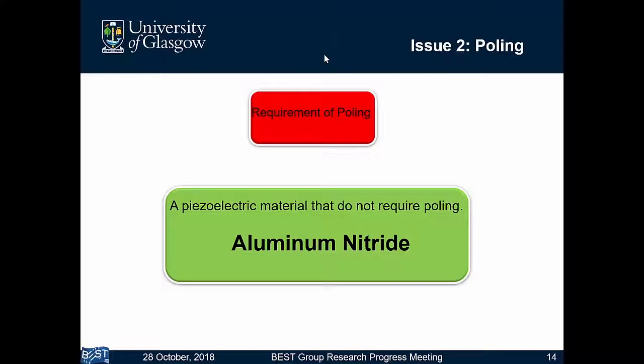The bad thing is that the piezoelectric coefficient is a bit lower compared to PVDF-TrFE, but still we see the advantage that it cannot damage my device. Anyway, we can increase the sensitivity with an amplifier, so this requirement can be fulfilled by aluminum nitride. The next step was how to deposit aluminum nitride, because the issue with aluminum nitride is that it shows the piezoelectric property only when it grows in a certain direction.